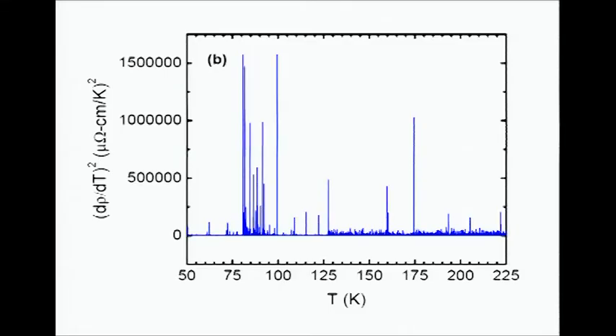If you probe this hysteretic region very slowly, you can in fact get a noise spectrum of thermal spikes. This is caused by scattering off the intermediate beta phase. You can look at the statistics of these spikes and get a picture of what is going on at the interfaces, and we see carrier localization at the interfaces, consistent with the Mott picture.